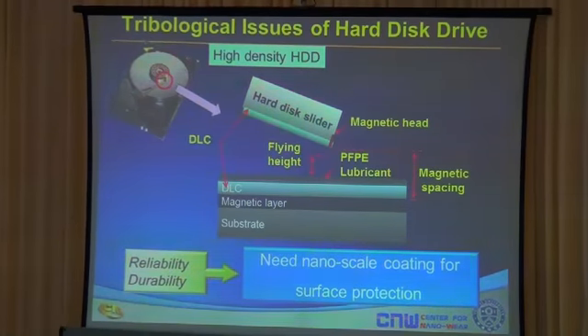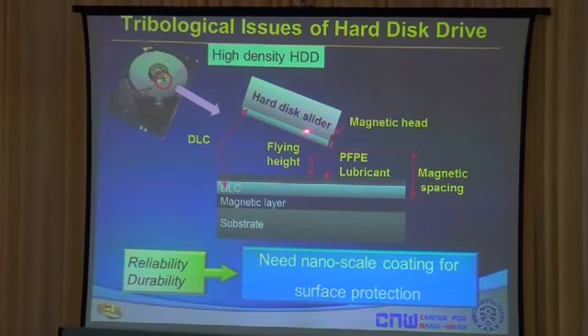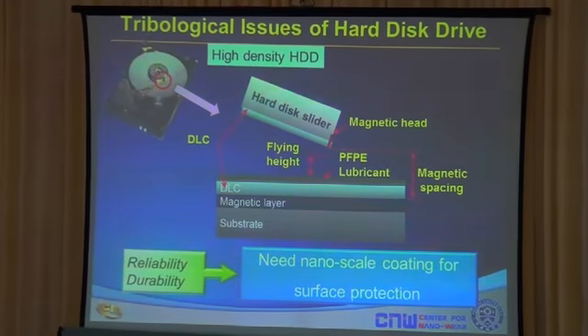If you look at the hard disk drive, it's composed of a slider head on a magnetic disk. The magnetic disk is composed of several layers, and the slider flies over the disk at a very low height. The height is only about 10 nanometers. Now, there's an incentive to lower the height so that the head can be closer to the magnetic element. In this case, the recording density will increase. So the industry is trying to lower this height further and further. And right now in today's hard disk drive, if you buy a hard disk drive, the flying height is only 2 to 3 nanometers. It's just mind-boggling to imagine that the slider is flying at that height.